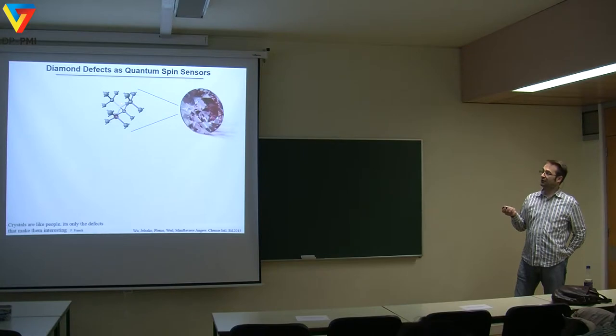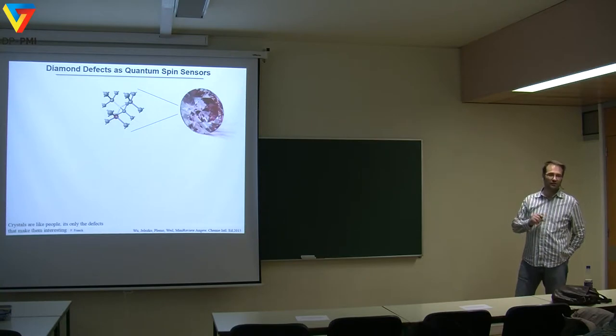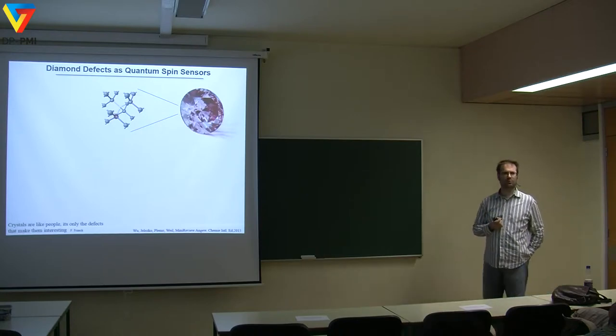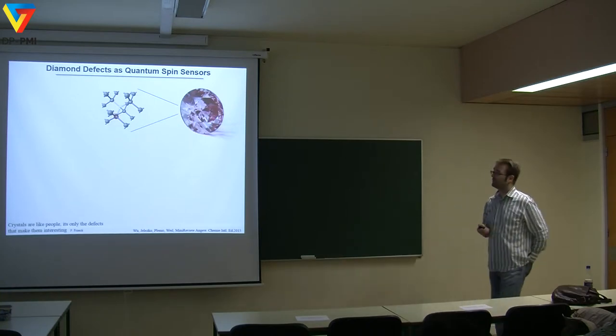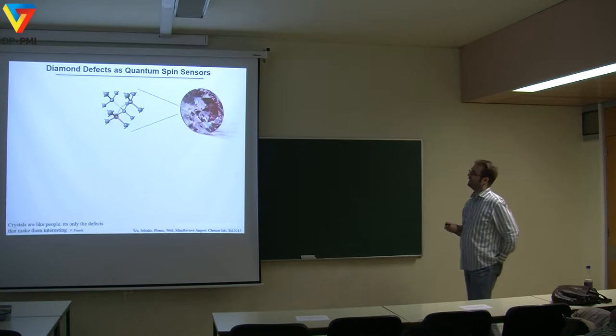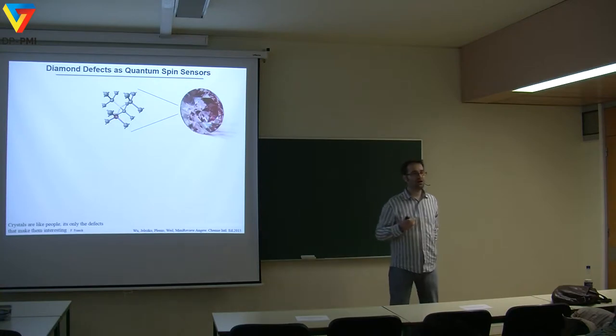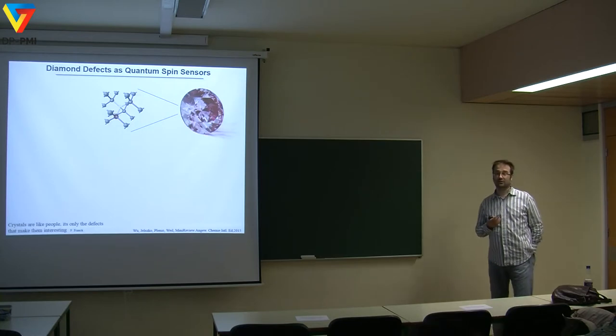You have here a diamond with atomic-size defects that absorb and emit light. You can make a very small diamond—a few nanometers in size—and if it has one of these defects, you shine laser light on it and it will scatter roughly 10 to the 7 photons per second, about as much as a quantum dot. So you can see it in a microscope. This is already an interesting way of tracking where these little diamonds might go in a cell. But for what we want to do, this is not good enough on its own.